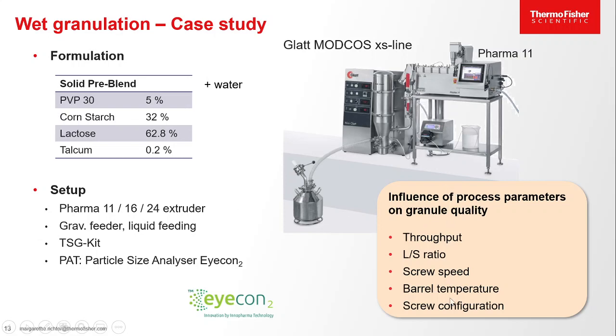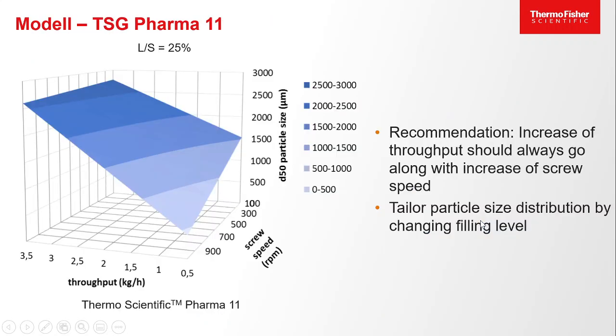And if we check all these process parameters, what's the influence of the process parameters on our granules? You'll see there's quite some impact. Here we have a summary of the throughput and the screw speed. So if we increase the throughput on the Pharma 11, for example, coming from 0.5 kilogram per hour up to 3.5 is probably challenging. So this is a model based on some trial results we have.